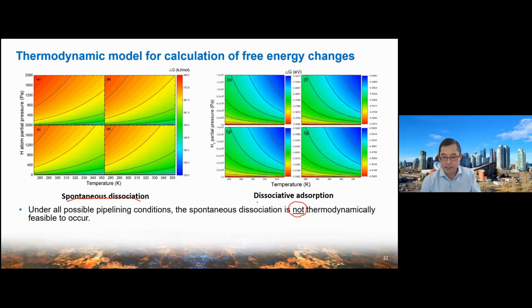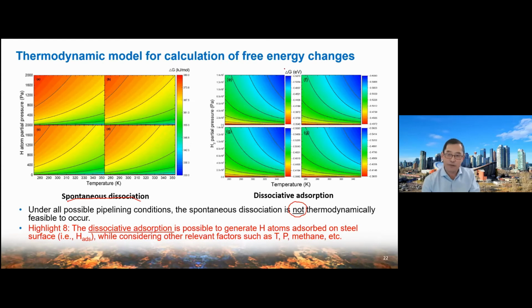The second mechanism is dissociative adsorption, and here you can see from the free energy change that under the pipeline operating condition, delta G, the free energy change, is negative. A negative free energy change for this mechanism means it is thermodynamically possible to generate hydrogen atoms, but you need to include the influence of temperature, pressure, and composition, particularly the methane percentage. Then you calculate the free energy change and determine whether it is thermodynamically possible or not. Our calculation proves this mechanism can make hydrogen atom generation happen, and the hydrogen atoms go into the steel.